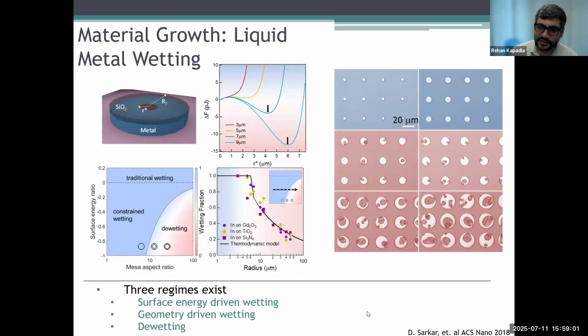So that's the physics of what we're calculating here, which is, what is the free energy change of a template without a void versus with a void as a function of this void radius. Just for everybody, if the free energy change is above zero, it means it's not thermodynamically favorable. If it's below zero, there's a lower energy state my system can drop into, and so it will try to do that. That's the basis of our model, and that's what we see here.